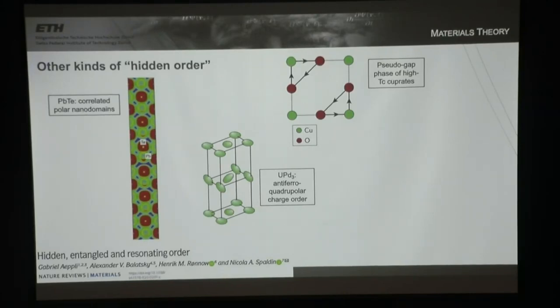Well, some of the actinide materials, where there's very strong spin-orbit coupling and complicated multiplets of the electrons, have orders that are very difficult to measure directly. And this was an interesting one. There was a divergence in the specific heat, but no apparent change in the structure. And it was found, again by neutron scattering, that it has an antiferro charge quadrupolar order. So I've tried to draw the quadrupoles. These are the charge quadrupoles on the uranium atoms. Subsequently, this was also found to have a structural distortion. Of course, if the charge of the electrons order, the structure has to change too, but it was so tiny it could not be detected at first.